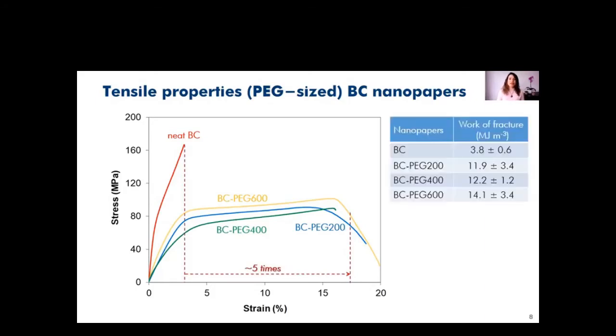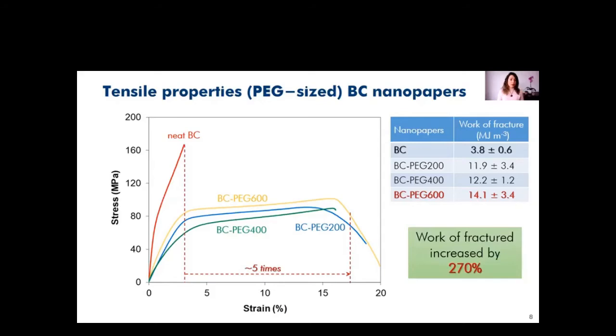And the work of fracture of the neat BC was measured as the area under the curve, and it was found that the work of fracture of neat BC is about 3.8 megajoules per cubic meter, and that it was further improved up to 14 megajoules per cubic meter. And this improvement in the work of fracture means 270% of improvement, which is a high improvement.